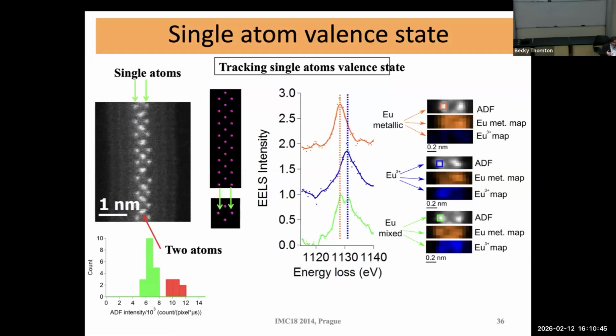This is a very interesting discovery for us. At that time we didn't have very fast detectors, so we could make only very slow mapping, but most of the europium atoms show both states at that time. So only one atom stays 3+, and the other atoms show the mixed state. This means our shutter time is not short enough to track the electron transfer, because if we take one spectrum, it's always sometimes mixed. This one is from mixed atoms, this one is 3+, and this one is metallic.